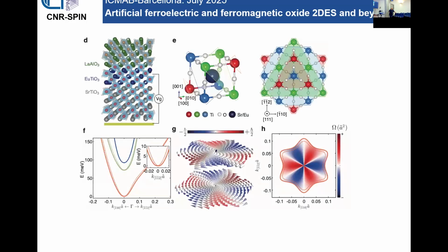On the other hand, in our LAO-ETO-STO system, for structural reasons, we are lucky, because the trigonal crystal field splitting is quite large. So really we can tune the Fermi level, for example, only in the lowest band. And in this case, if there is no time reversal symmetry breaking, if the system is non-magnetic, the physics is a trivial physics of a two-dimensional electron gas.